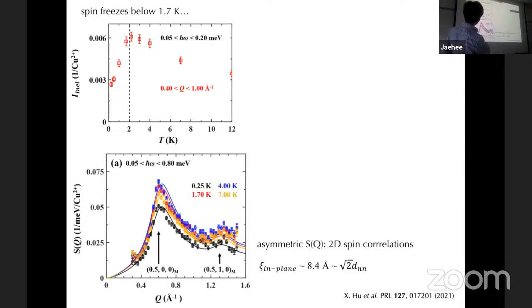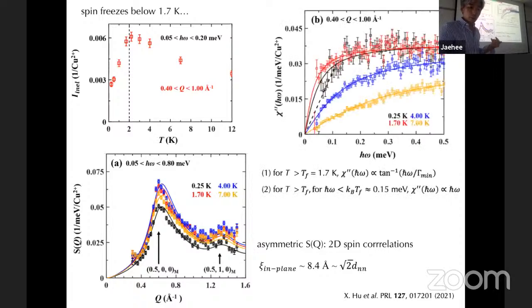And also this elastic, you have this nice asymmetric shape, and we can fit this to the two-dimensional correlation function and extract the in-plane correlation length, which is the second nearest-neighbor interaction distance. So J2 is strong, that also. And then we also plot the chi double prime as a function of omega, and at base temperature, in fact, it is linear up to 0.1 meV, which corresponds to 1 Kelvin. Also 1 Kelvin, so it's close to a TM.